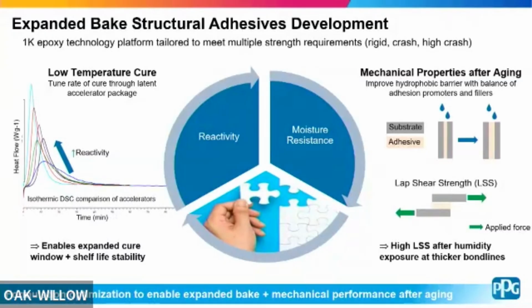And you can achieve that with different accelerator packages, right? However, what we found was once you do that, you get a more reactive product, you actually lose shelf stability. So that's not ideal. And so the team has spent a lot of time working on optimizing that accelerator package so you can achieve that low temperature cure while maintaining that long-term shelf stability that you would need. So here I'm just showing a basic DSC graph showing heat flow versus time. So you're really just seeing, you can change your accelerator, tune that reactivity, or find a balance of reactivity so you can enable those two different properties.